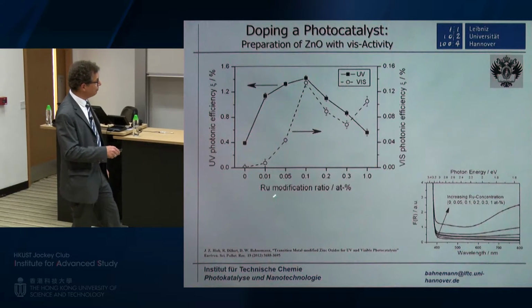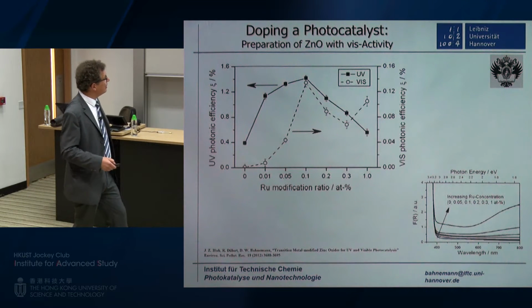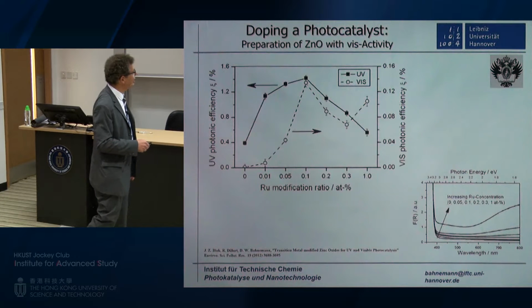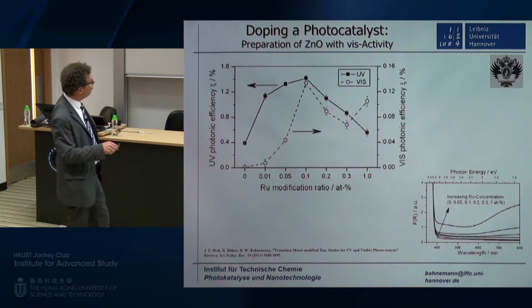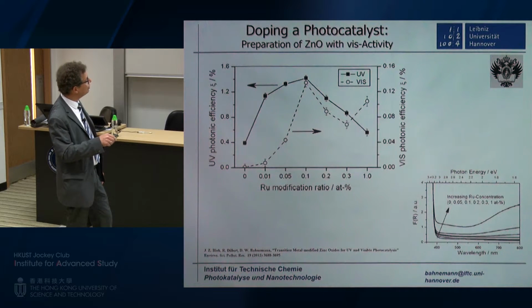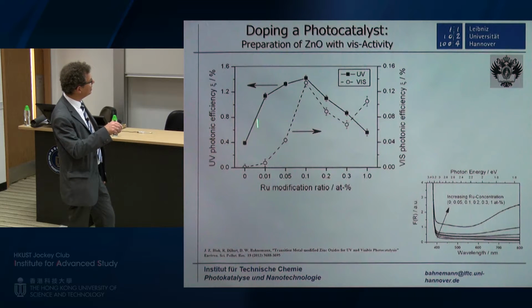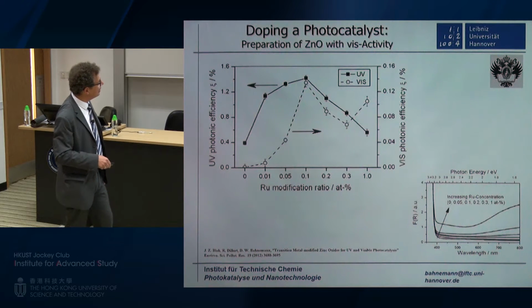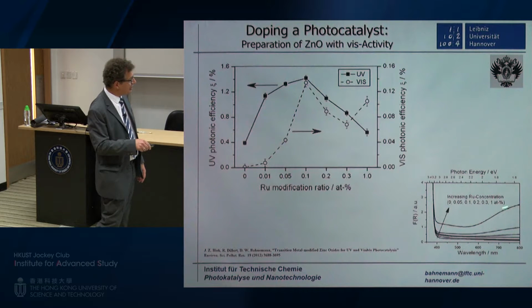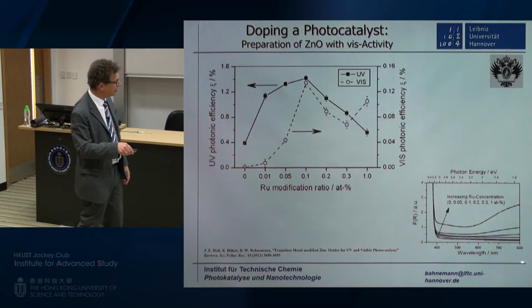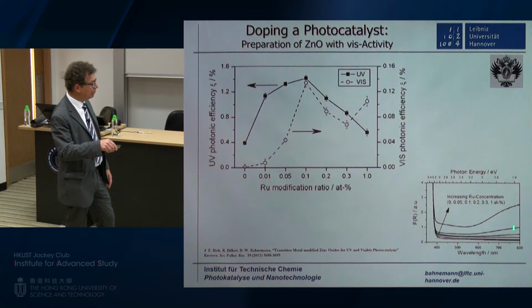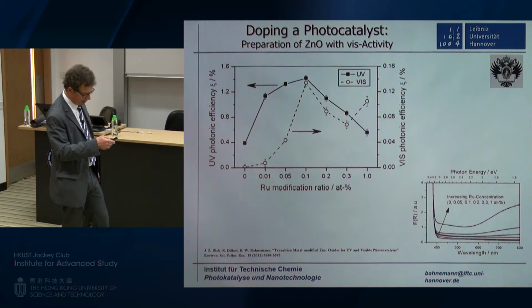With ruthenium as our dopant, we found another interesting thing, and this is that we now found once again a visible light activity at high modification ratios, doping ratios, but also the UV activity was not highest at very low doping ratios, but was highest at about 0.1 atom percent. And again, we find very strong coloration. Now the absorption maximum is already in the near infrared.